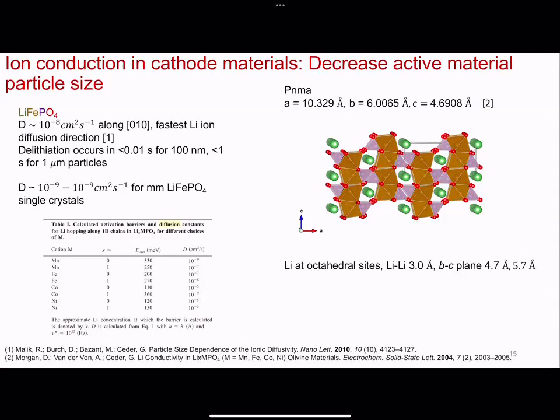Okay, well, what does that have to do with decreasing the active material size? Well, if you make lithium iron phosphate smaller and smaller, down to the 200, the 100, the 60 nanometer regime, how many sites do you have when you have a 60 nanometer particle? You don't have to answer that. That's actually a rhetorical question. I wasn't expecting anybody to do the math in their head. But that's what you ask yourself. Statistically, if I have a smaller particle, I have a smaller defect concentration because there aren't as many sites for there to be even a defect. And in fact, it's like 2 defect sites in like 16 nanometers. So that's all to say, if you decrease the size, then you decrease the defect sites, which means lithium ions can diffuse faster because there's not a lot of blockages.